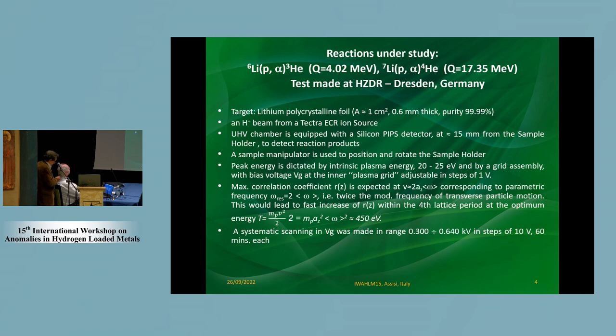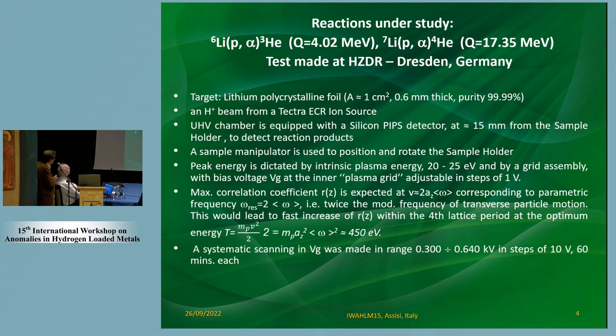So what have we done in practice? The reaction under study here is just a proton impinging on a lithium target. You know, lithium is mainly 95% lithium-7. And the test was made at the Rossendorf laboratory in Dresden, very well known. We had a lithium polycrystalline foil. We used the proton beam from an ion source. We had the silicon detector, sample holder, sample manipulators,